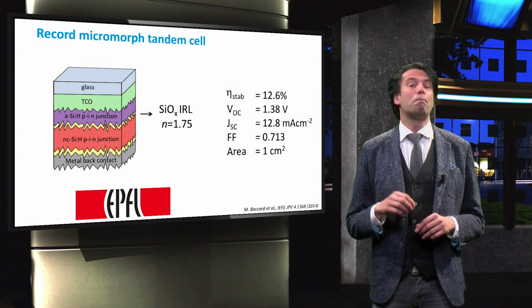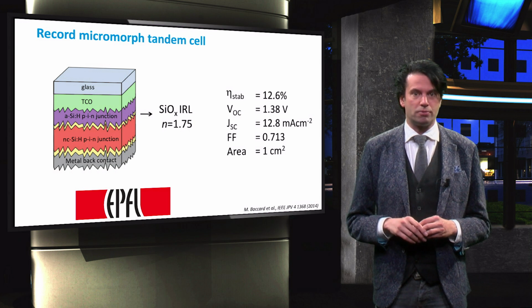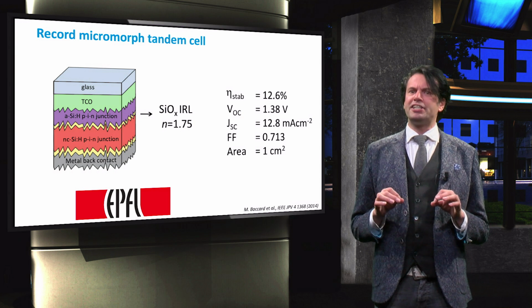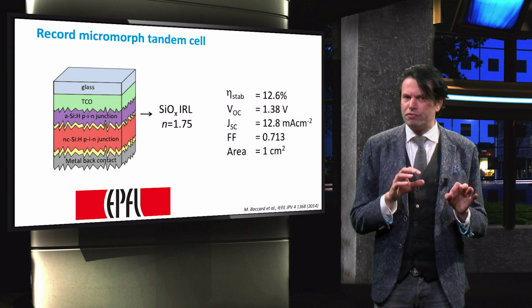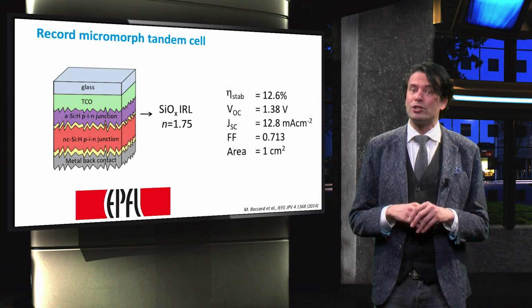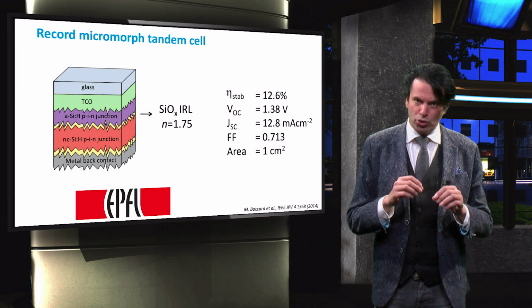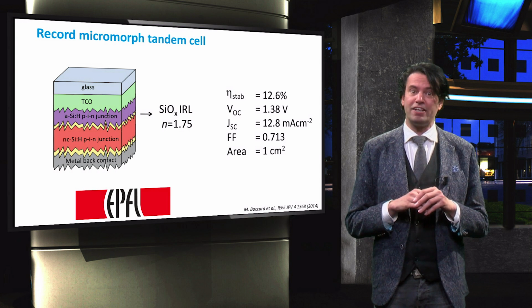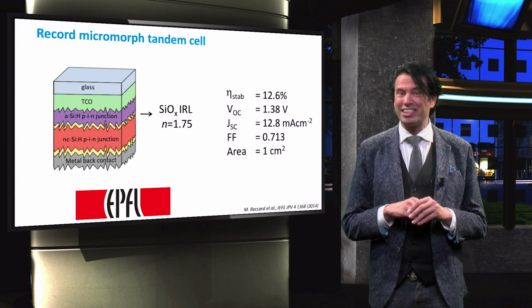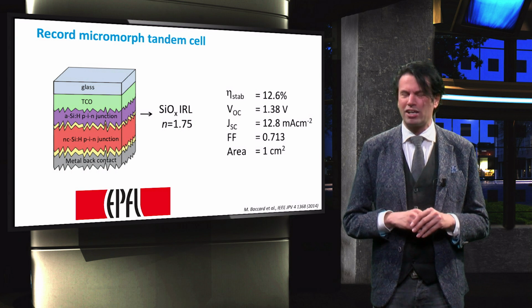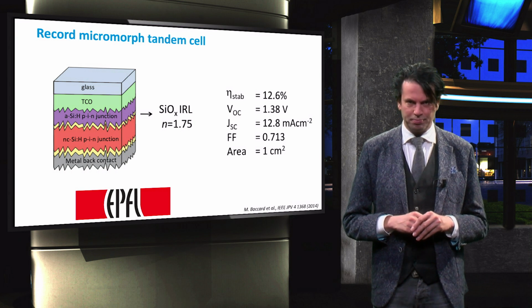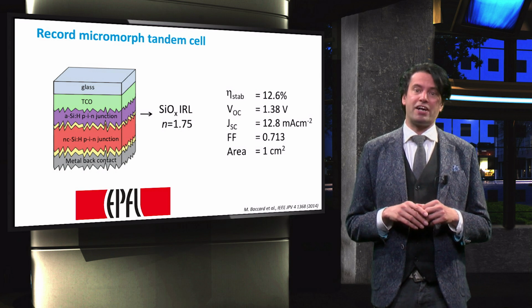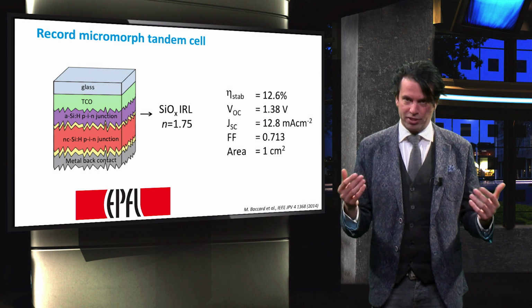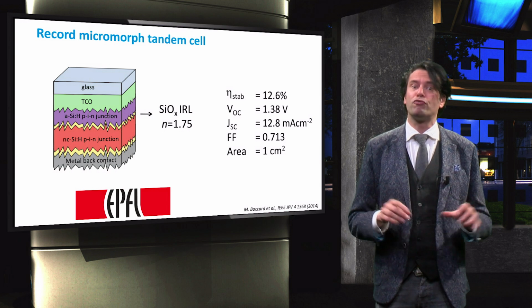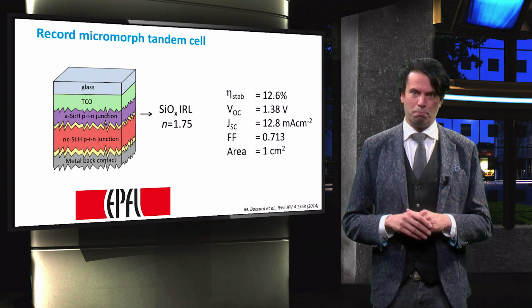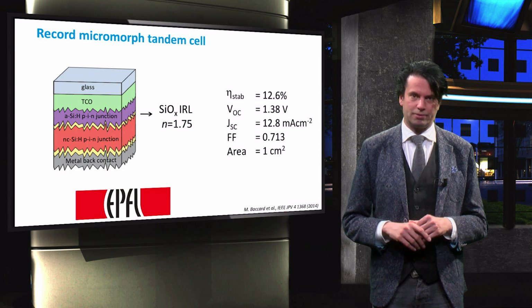Then the amorphous silicon PIN junction was deposited. The important innovation is that a 70 to 150 nanometer thick N-type silicon oxide layer was deposited with a low refractive index, namely 1.75 at a wavelength of around 800 nanometers. On top of this intermediate refractive layer, a conventional N-type nanocrystalline silicon oxide layer was deposited, followed by the nanocrystalline silicon bottom cell and the back contact.